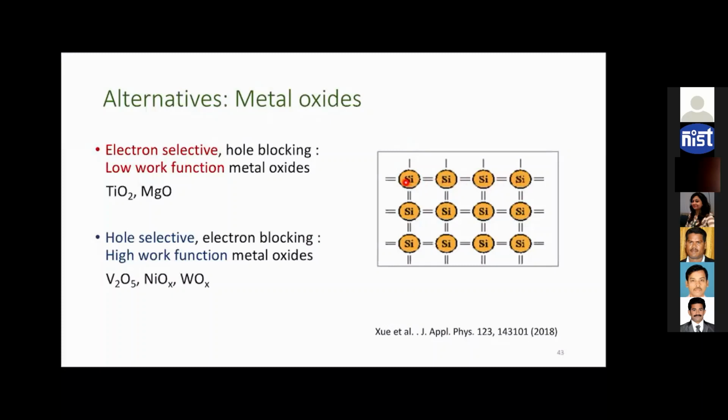The advantage of using an amorphous material here is that it can relax its structure, because now there is no bound for it to sit on a particular fixed lattice site, right? So whenever you are using amorphous oxides or amorphous materials, there is a fair amount of possibility that they are going to passivate the dangling bonds.